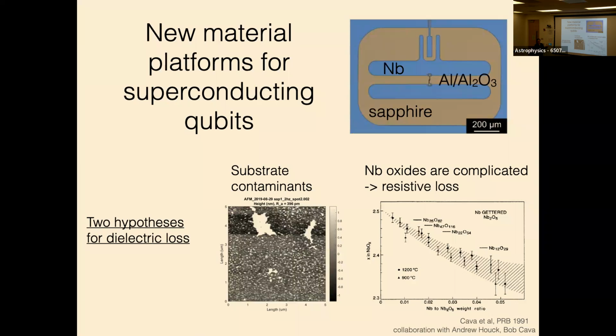The first is just really dumb substrate contaminants, right? It's that if you don't do a good job of cleaning, then there's all this stuff that's there, and that could lead to loss. The other possibility is what Bob pointed out: he had spent a lot of the 80s and 90s studying the oxides of niobium, and he said it's just a big mess. Niobium oxides are super complicated. You get every single type of stoichiometry. And he thought maybe we could see resistive loss from this because maybe you have a bunch of weird superconducting phases and things like that.